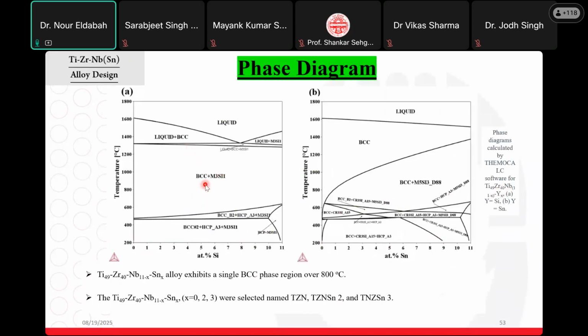For two important points, we have the existence of intermetallic M3Si1 with the BCC phase, and as I have said earlier, these intermetallics will affect the ductility of the alloy and consequently will not be optimum for orthopedic implantation.